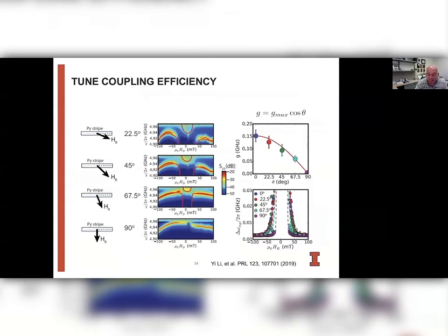Now, as I said, we had originally the magnetic field along the permalloy stripe, which allowed for the strongest possible coupling. Now we can rotate the direction of the magnetic field until it's perpendicular. And once it's perpendicular, the RF field and the magnetization are parallel and don't couple to each other anymore. And indeed, what we see is if we rotate the magnetic field further and further, the hybridization gap gets reduced until it completely vanishes here. And this reduction of the coupling constant can be explained by a simple geometric factor, as you would expect from the geometry of the system. So that means that we can also easily tailor the coupling strength in the system simply by reorienting the direction of the magnetic field.